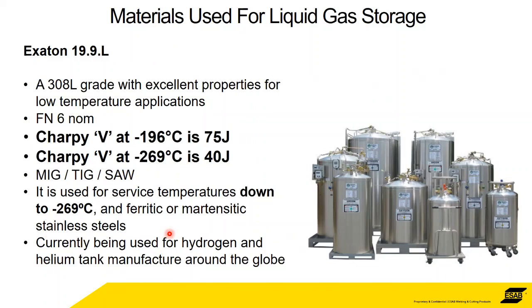The other grade that I want to specifically mention is this 308. We've got a 308L grade. Again, at minus 196, it's 75 joules, so it's even better than the 316. However, this is tested, it's approved. We've got approvals on this for minus 269. We've got a toughness value of 40 joules. So it's a practical solution, I should say, for hydrogen tank applications. So it's currently in use. It's becoming more and more prevalent.